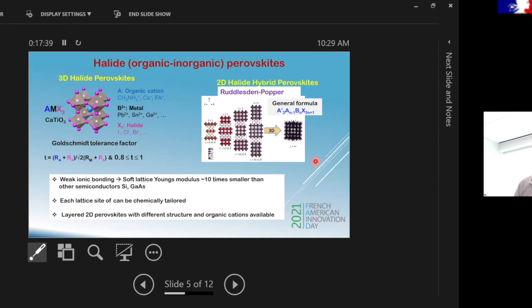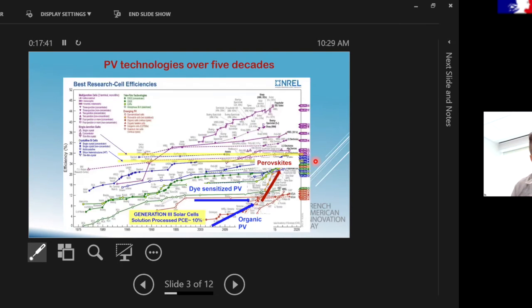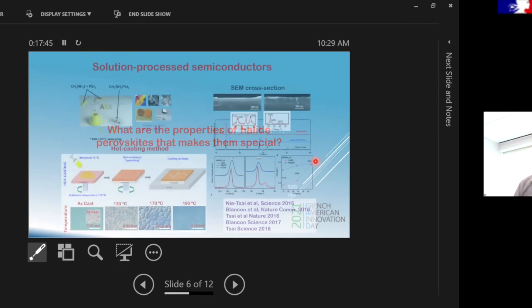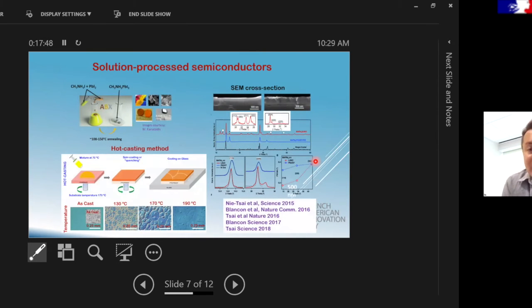Perovskites, on the other hand, are materials which you can take and put in solution, basically in solvents, and spin them on top of the silicon. And so you get a film on silicon, which is compatible and works very, very well. That's sort of the premise. So that's where the community is kind of headed. But in addition to this, perovskite efficiencies themselves are now at 25%. I think the bigger question is going to be about stability, whether these survive for 20 years. And there's also a lot of effort being put into this.